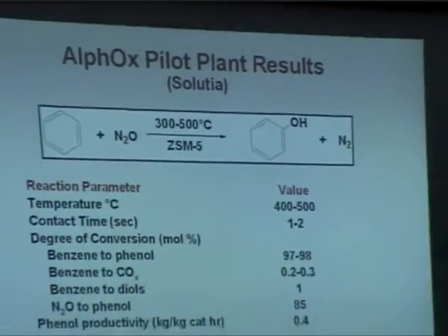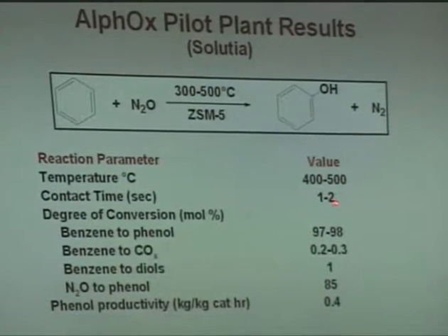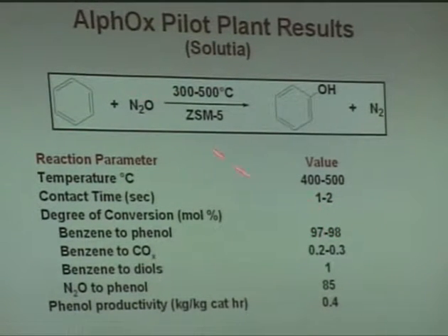So they actually built a pilot plant, and the results that I've been able to find so far look very, very encouraging. So the N2O is using this Panov chemistry, 400 degrees centigrade, 1 to 2 second contact time. Selectivity in their pilot plant, which they call AlphOx, which is rather appropriate, is very, very high at 98% selectivity. The productivity is 400 grams, 0.4 kilograms, per kilogram of catalyst per hour. Pretty decent productivity in that process. So all of these results are very encouraging. I don't think they have gone commercial with this yet, but they've certainly demonstrated that everything works out well in the pilot plant.